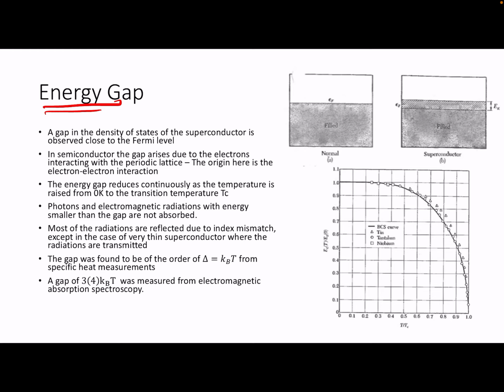But what happens is, let's say I have a material at 0 Kelvin, all the states below the Fermi level are filled, right? In a superconductor, there exists a gap in the density of states surrounding the Fermi level. So all the states below and above the Fermi level are separated by an energy value delta. This is called the superconducting order parameter. Below and above this delta are vacant. You have no states, no single particle states can stay in these energy levels. All the superconductivity is carried by electrons which are paired, called Cooper pairs, which live at the Fermi level here. This is a very different and interesting state which does not appear in the single electron approximations that we have seen till now.